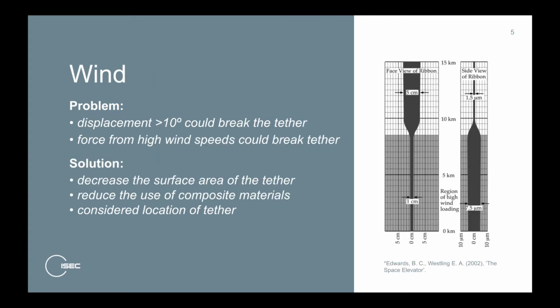Wind could also be problematic, as it could displace the tether and even sever it. Bradley Edwards, in The Space Elevator, writes that the tether could safely be displaced by up to 10 degrees from its normal, and that a ribbon made from 1,200 fibres of a 10 micron diameter would break at a wind speed of 116 kilometers per hour over a 1 kilometer segment.